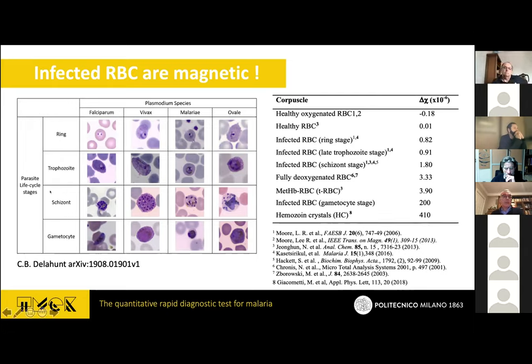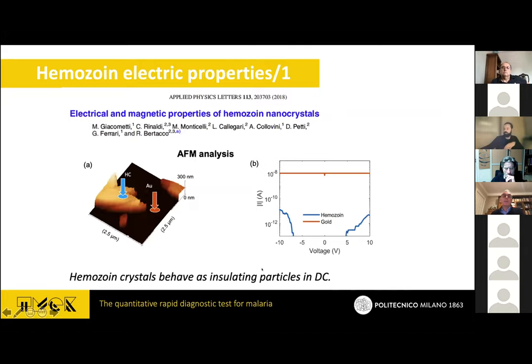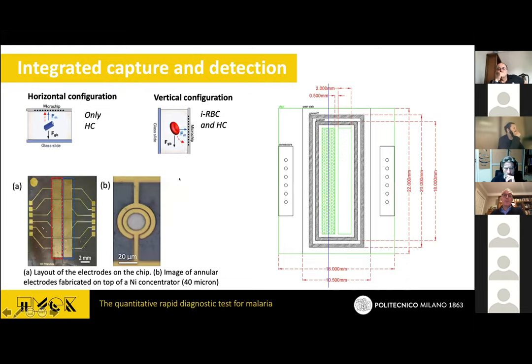And here you see the different stages that you can have for the different species of plasmodium. Now, at the very beginning, we tried to figure out which were the physical properties of these nanocrystals, and we discovered that they are insulating particles, both in DC and also at high frequency. This was a measurement carried out by conductive AFM, showing that on top of the hemozoin crystals there is a low current with respect to what you measure on the substrate made of gold. And that was good news because in principle, our detection method is based on impedimetric detection, which means we fabricate a chip on which we have some electrodes.